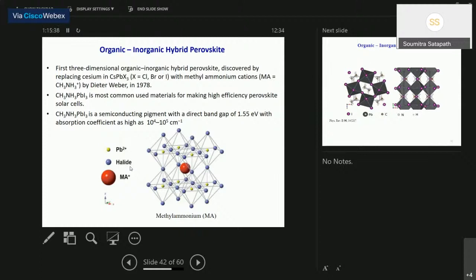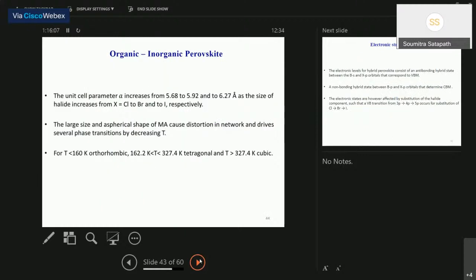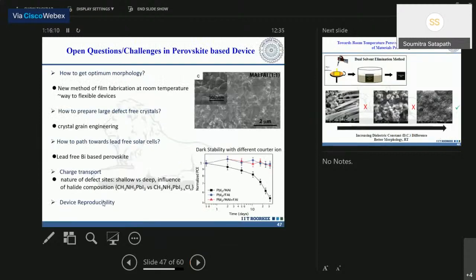When light falls on this CH3NH3+, this MA, this guy has a low activation energy. So it starts moving across the crystal structure. And if this red ball starts moving along the crystal structure, then the crystal structure is not stabilized. It disintegrates to the normal lead structure. It is a phenomenon called migration, a big problem in perovskite. And the last point, the challenge I mentioned, is that device reproducibility is a big question.